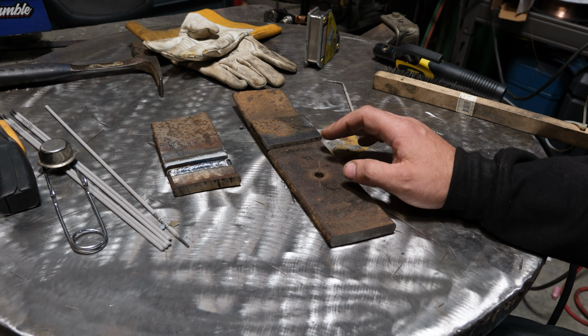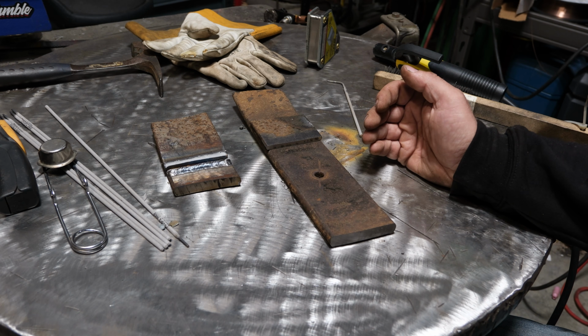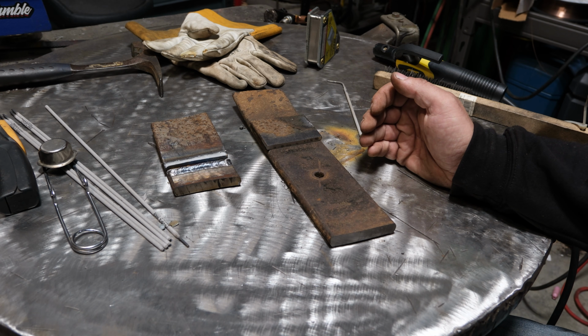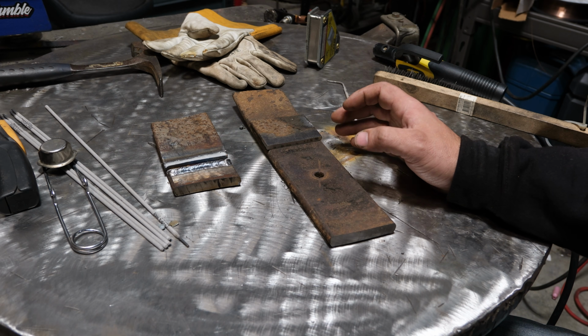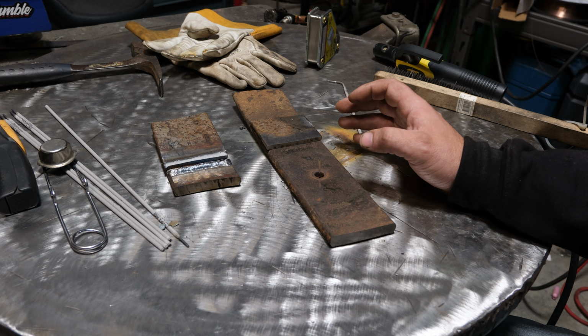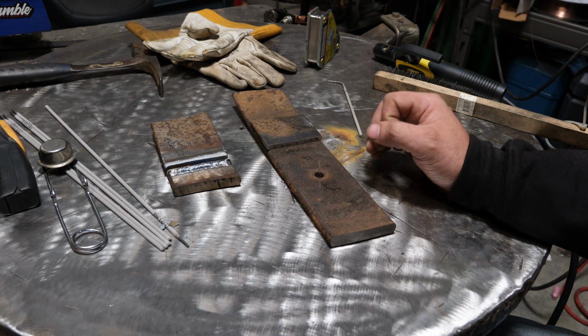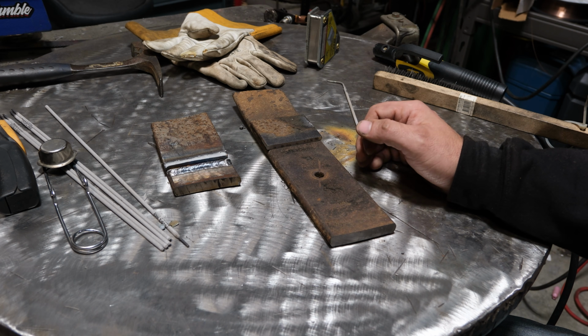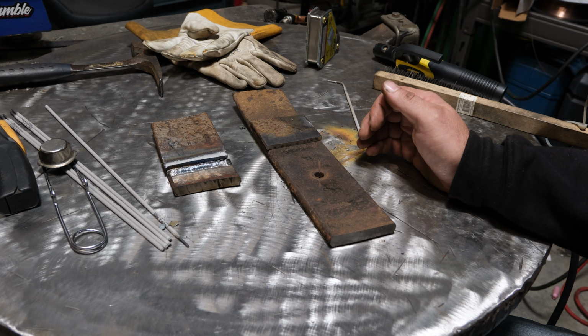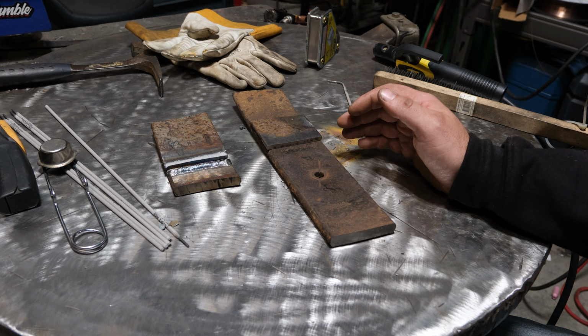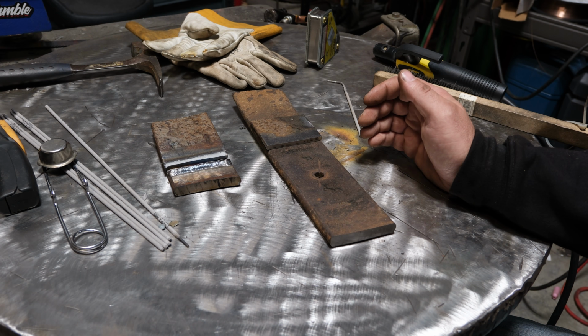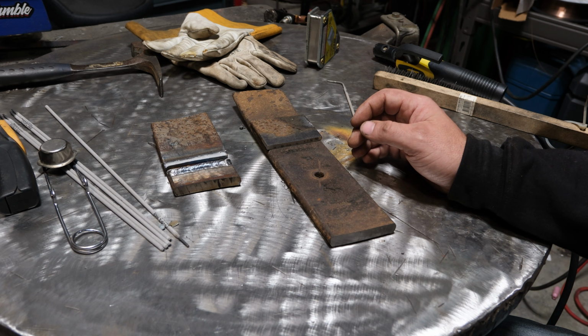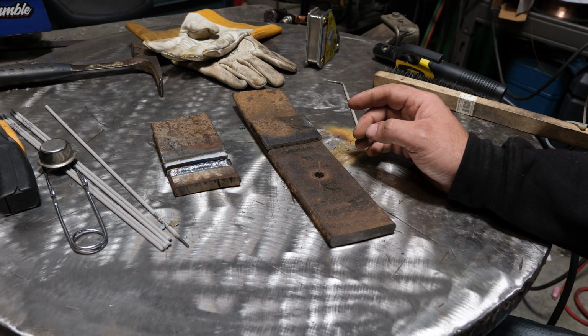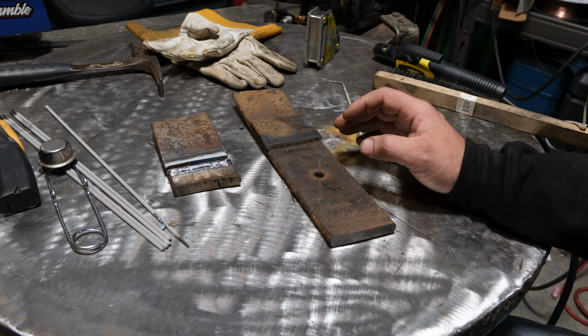Now, a lot of people, when trying to heat treat or temper this stuff, will heat it up to that dull red color and then quench it in oil. To me, as an emergency repair, you probably don't have much oil laying around, nor is it probably that smart. And I know that heating it to dull red and letting it air cool will get a leaf spring to get you off a trail or out of an emergency situation. So my opinion is I would not go and screw around with oil, because if the oil is super cold for some reason, like it's in the back of your vehicle, is cold outside, and you go and dip that steel, you can have a drastic effect on it, more so than you would think.